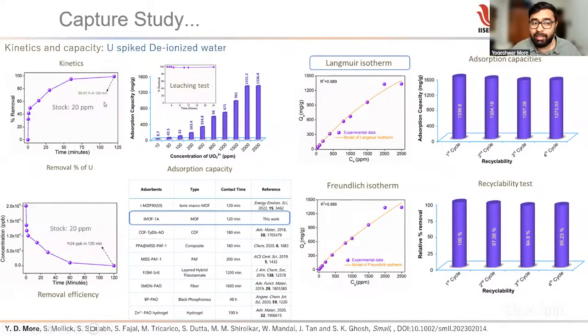Why does this kinetics time matter? In order to reuse the adsorbent, that is the MOF, for uranium extraction, we need the lowest time. If it takes days, then the reusability of the adsorbent goes down, and we won't be able to extract a higher amount of uranium in a smaller time. Also, the higher the exposure, the more the MOF stability goes down. So for the capture in DI water, our MOF stands second in the literature.